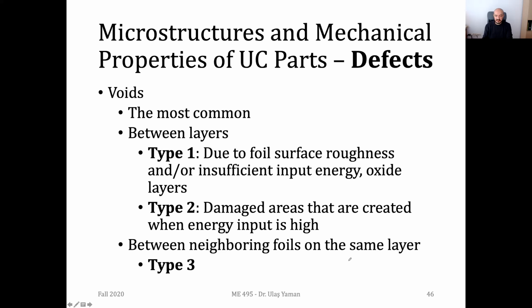So if you remember from one of our initial sketches, illustration of ultrasonic consolidation, if this is the top view, once the width of your part is too much, then you may have, let's say, 3 sheet metals actually deposited on the same layer. But while you are depositing, probably you will have some gaps here, right? It will be quite difficult. You may have kind of a gap in between the neighbor foils, and this is called a type 3 defect in ultrasonic consolidation or ultrasonic additive manufacturing.